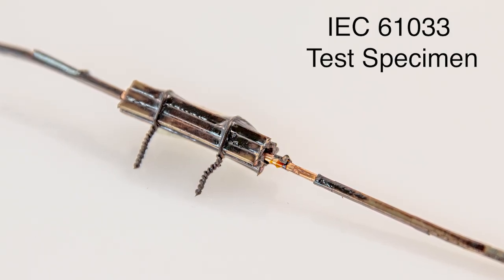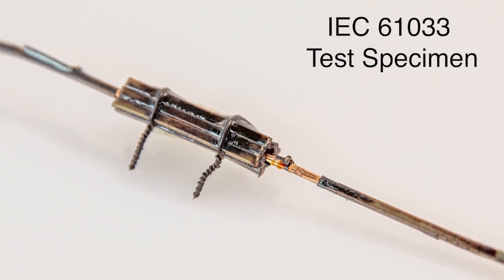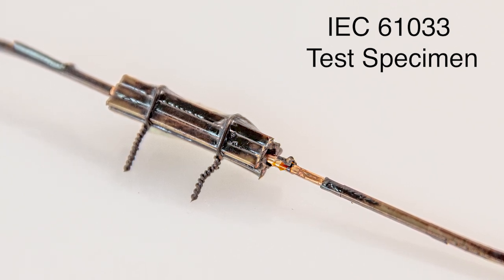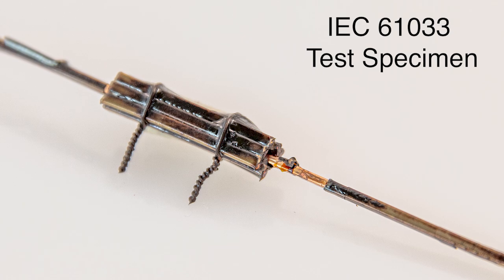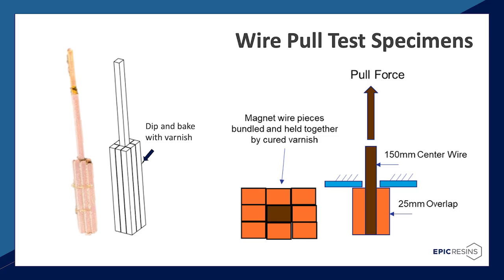Adhesion alone does not assure success as a secondary insulation. Adhesion must be maintained when exposed to elevated temperature conditions and harsh environments. For secondary insulation materials, this is tested using IEC 61033. This is a 61033 test specimen. As you can see in the illustration, this bundle is composed of 9 pieces of PEEK-coated conductor wire.